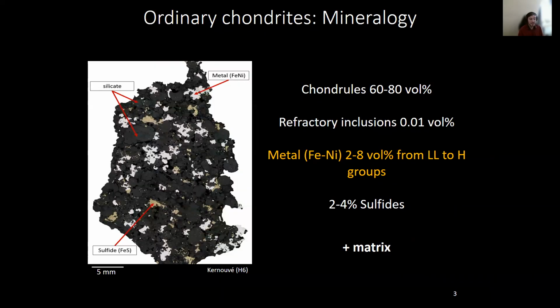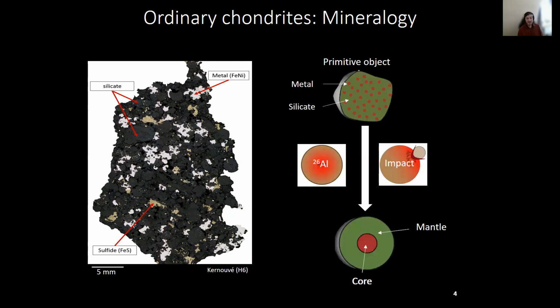So to do that, we are using meteorites, and within the numerous meteorites groups, one of the best candidates to study metal phase formation are ordinary chondrites. And this is because they are composed of pristine silicates, metal and sulfide grains, which means that they haven't experienced planetary differentiation, meaning that the metal and the silicates haven't been segregated into a silicate mantle and a metallic core to form a planet. Therefore, this kind of object seems to be samples of early formed undifferentiated planetesimals.